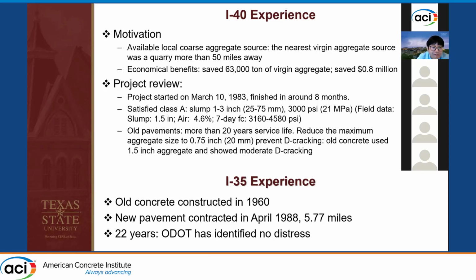And for the I-35, we did not find a lot of information compared to the I-40 case, but we know the old concrete which supplied the RCA was built in the 1960s, and the new RCA concrete pavement was constructed in April 1988. And Oklahoma's DOT actually had a chance to go back to the I-35 CRCP sections 22 years after 1988. So it's like the beginning of 2010. And they did not identify any distress.